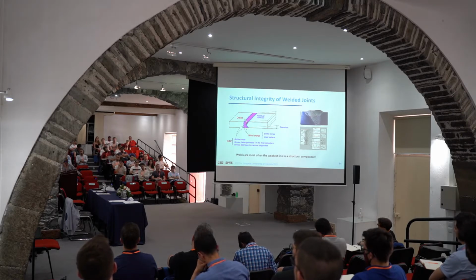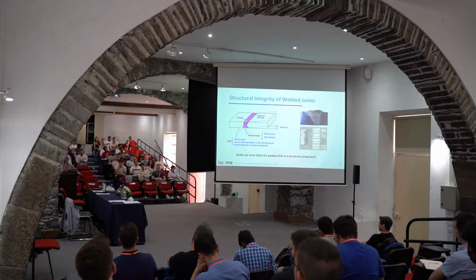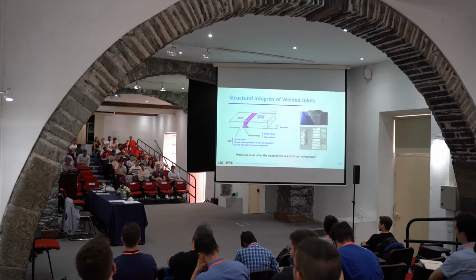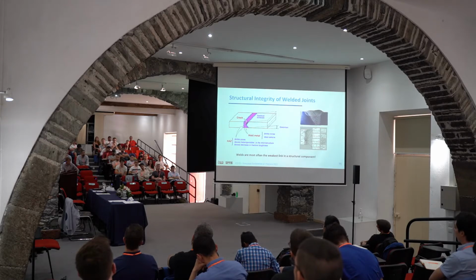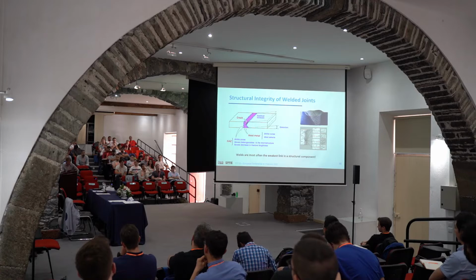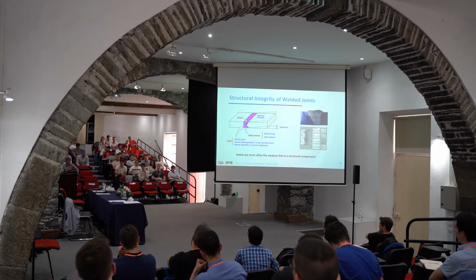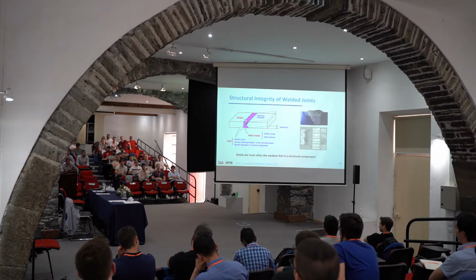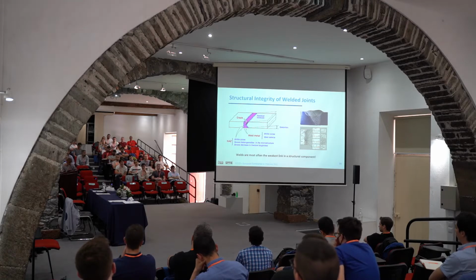Even in a nuclear reactor, the pressure vessel, the most important component in a nuclear power plant, is welded. As a matter of fact, the main concern in the nuclear reactor is what they call the weld belt around the pressure vessel, and that's because welding is a thermal process. So again, at the shipyard or the pipe industry, you get a plate, you make the pipe and then you have to weld it. The thermal process will make things very different, because you have first a non-controlled thermal process.